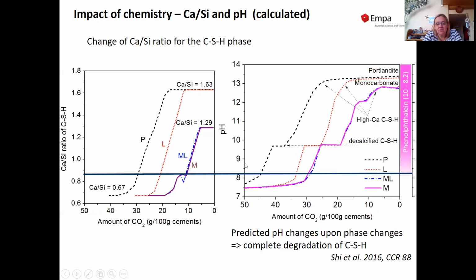the metakaolin and metakaolin limestone cement, or we can plot here the pH. And again, we realize we can add much more CO2 or bind much more CO2 before we observe the drastic drop of pH, which is indicated by the phenolphthalein test.